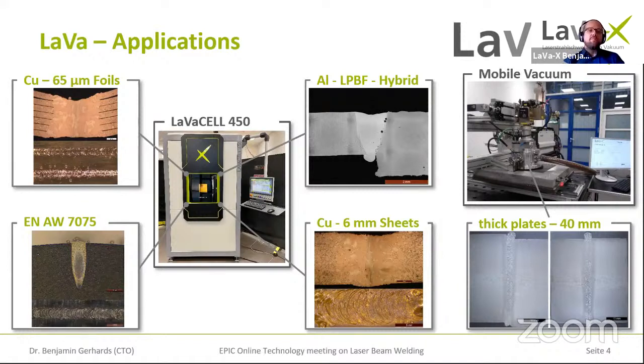Furthermore, we have excellent qualities when welding aluminum alloys. Displayed in the lower left picture, you can see a weld in 7075 aluminum, and you won't find any cracks in those welds. As well, if you look at the weld surface displayed at the bottom of the picture, you can see that the surface resembles a weld conducted on stainless steel more than on aluminum.